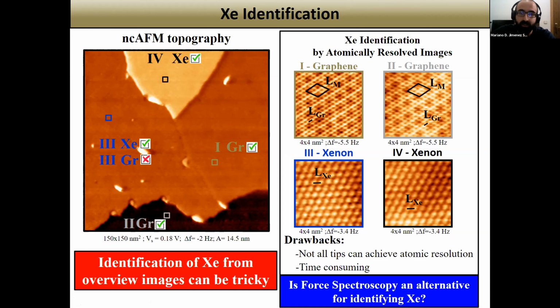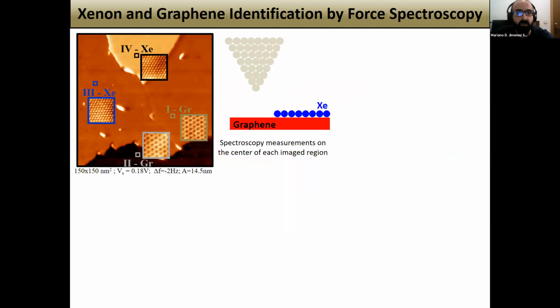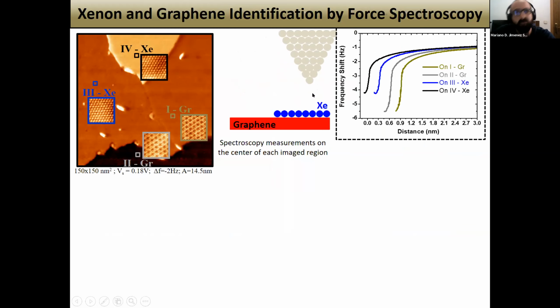So the question is, can we employ force spectroscopy as an alternative method for identifying xenon in a faster and tip-independent way? Well, in order to answer that question, we have performed spectroscopy measurements on the center of each imaged region, keeping the tip apex constant. From that, for this measurement, we have acquired these frequency distance curves, where the color again indicates in which region they have been acquired. The distance axis here is arbitrary. Well, what we observe in these curves are differences in the maximum frequency measured.